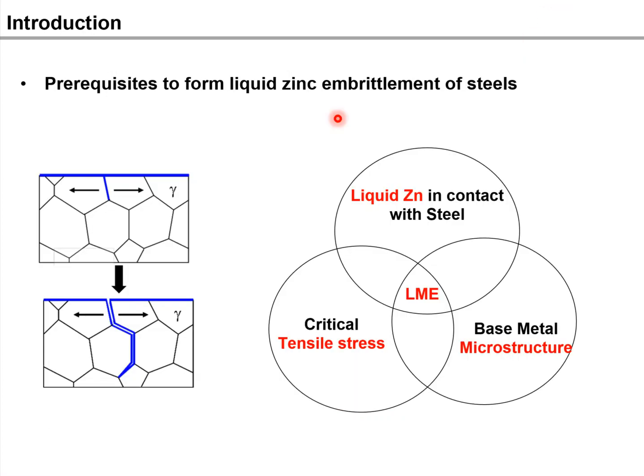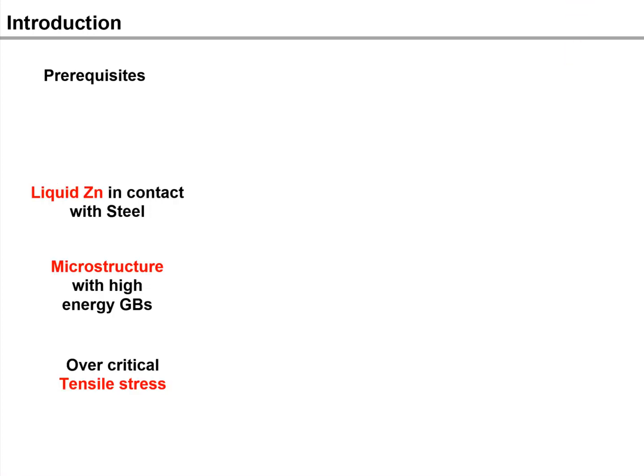Based on the observed LME cracks, the following three factors are the main prerequisites to form LME of steels. First, liquid zinc in contact with the steel. Second, overcritical tensile stresses. And third, base metal microstructure. When these three conditions are met at the same time, the LME crack will occur.